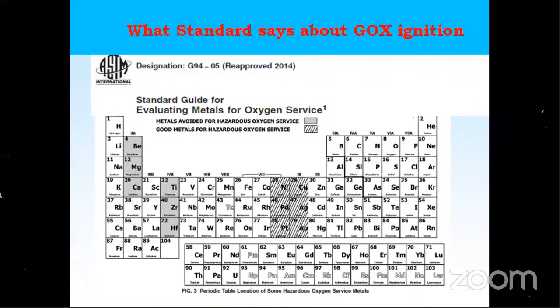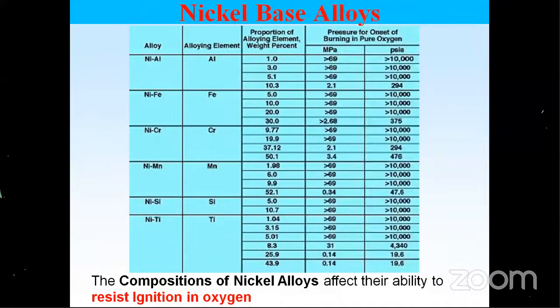What SpaceX has done is make a casting of this alloy, because the workability is so poor. They made one casting, which they machine and use in the form of a turbopump where hot oxygen is passing, and I think they will be using it in their new Raptor engine. In nickel alloys, these are the common alloying elements. When you add aluminum up to 5%, no issue. We have a pressure at which burning in oxygen is happening, up to 69 MPa.